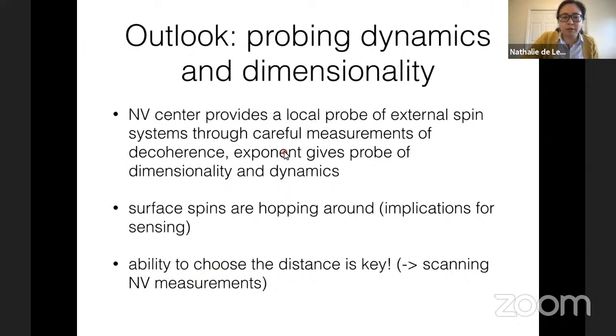Okay, so just as a very quick summary, what we've shown is that the NV center provides this really nice local probe of external spin systems through very careful measurements of decoherence. Specifically, carefully fitting this exponent gives you this nice probe of the dimensionality of the bath that you're looking at and the dynamics. In this system in particular, we find that the surface spins are hopping around, which has a lot of implications for how you might use these things as sensors.